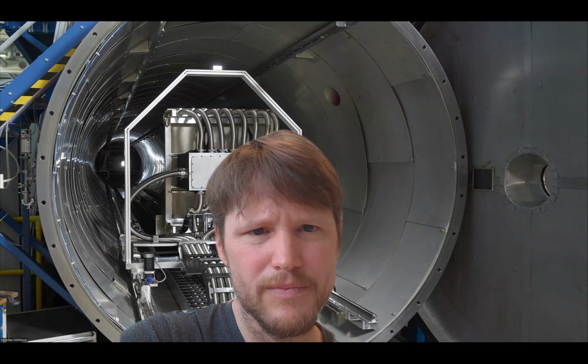Let's say I give you a rocking curve, and then you can. I think that would be the QZ, the QZ distance. So usually a Bragg reflection is found at some specific position in physical space. So once we rock the sample, we want to know the width of this Bragg reflection along the QZ direction. And so, what does the width tell you? If you see a width of, I don't know, tenths of a degree in a rocking scan, how can you compute the correlation lengths along the field? What do you need to do?